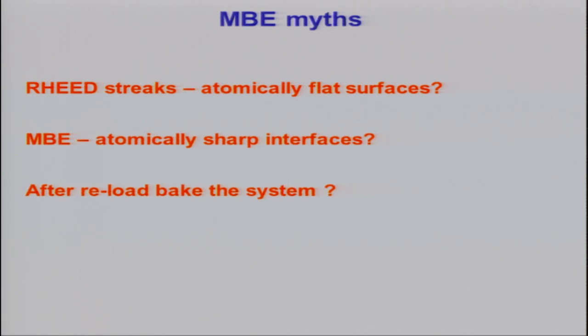The second thing I read in everything is that MBE gives atomically sharp interfaces. Complete nonsense. When you look at the surface with scanning tunneling microscopy, the interface extends over 2 to 3 monolayers at the minimum. So this statement, again, is completely wrong.